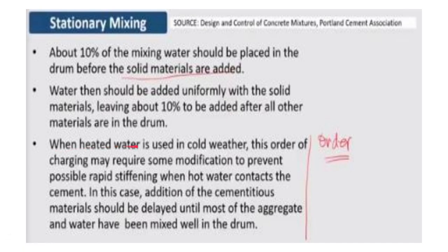When heated water is used in cold weather, this order of charging may require some modification to prevent possible rapid stiffening due to the high rate of hydration when hot water contacts the cement. In this case, addition of the cementitious materials should be delayed until most of the aggregate and water have been mixed well in the drum.